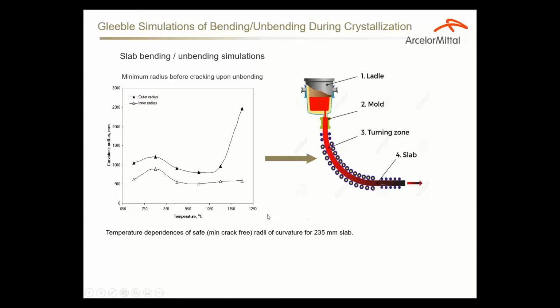Of course, the susceptibility to fracture during crystallization depends on caster configuration, casting speed, and of course on chemistry. So when we provide this kind of data to the mills for the given chemistry, that helps them to adjust the casting speed, temperature distribution in the mold, and they find that very, very useful information because it can help them prevent slab cracking.